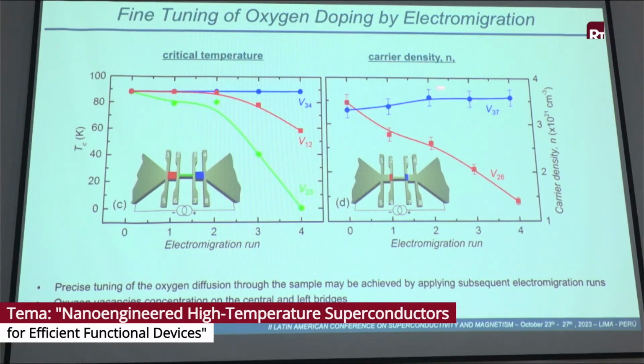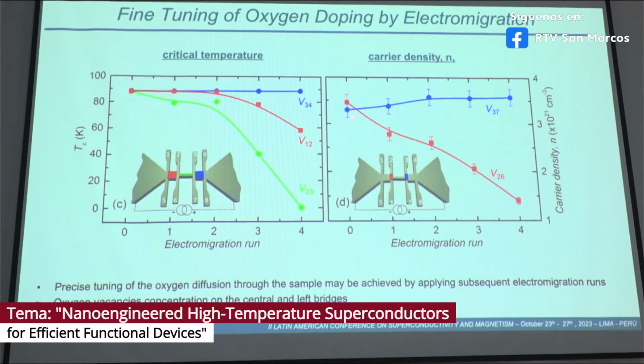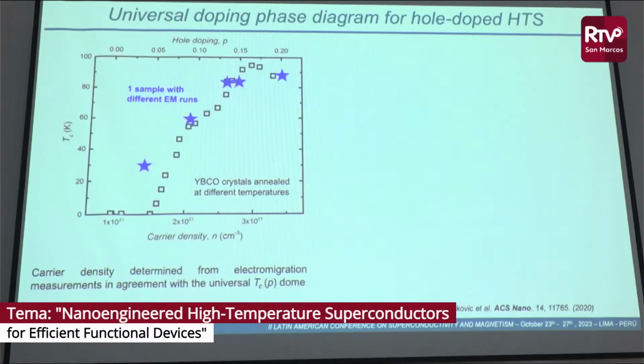And the same is observed when we observe the carrier density. The carrier density at this part of the track, the blue one, is increased a little bit, because what we do is move the oxygens in this direction, so we increase the doping a little bit, and here we introduce a lot of oxygen vacancies, so in this case the carrier density decreased.